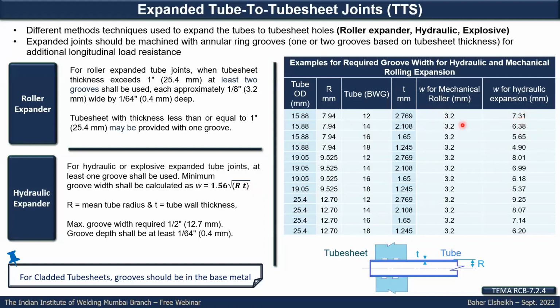By experience of some of the manufacturers, it is very important to maintain a little bit higher width for the hydraulic expansion to have proper sealing. Especially in the hydraulic expansion, the tube will take the shape of the groove because you will apply a pressure here, as we'll see. So if the groove width is very small, the tube will be forced to take this shape, and it will have a localized high expansion, which might cause stress concentration at the edge of the groove, and in future it might lead to cracking or stress corrosion cracking for some surfaces.